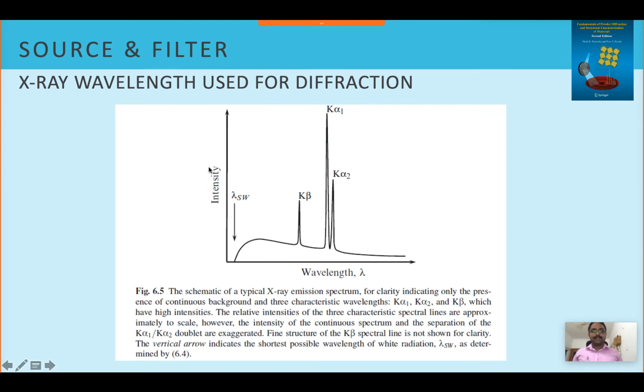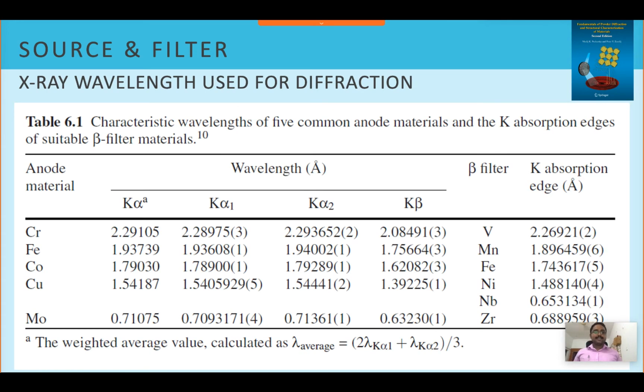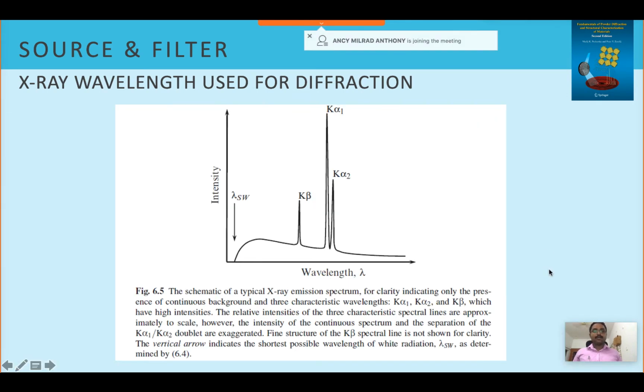According to this diagram, you can understand that this is the major intensity of X-rays coming out when you stop fast moving electrons using those anodes. So K alpha 1, K alpha 2, K beta. K beta is not required, so that will interfere with your data. So we will remove that. How to remove? You see this column called filter. For example, for copper, nickel is the filter, that is the next element. When you have the next element, nickel, placed in front of copper, the X-rays coming out will be stripped off of K beta. So K beta will not come out.